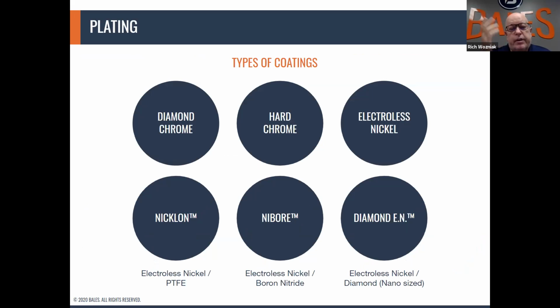Some other things to be thinking about is plating. We do 2 types of chrome, 4 types of nickel here. The diamond chrome, what's nice about that is the abrasion protection at an 85 Rockwell. Hard chrome, you're typically sitting at tried and true around 70, 72 Rockwell. It's good all around, food grade coating.